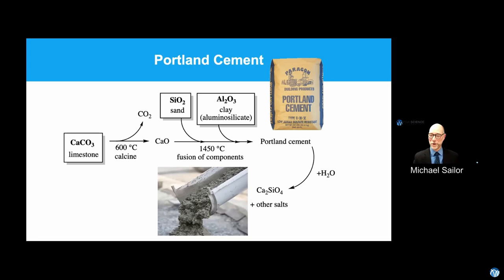I use this chart in my lectures to my inorganic chemistry class, so bear with me. All you need to know are your two most important ingredients in making cement: calcium oxide and silicon dioxide, sand. They usually put aluminum in there too, but you don't need to do that. Mainly the silicon dioxide and the calcium oxide. You put those two together, you get them wet, and they will set up after a while and make calcium silicate.